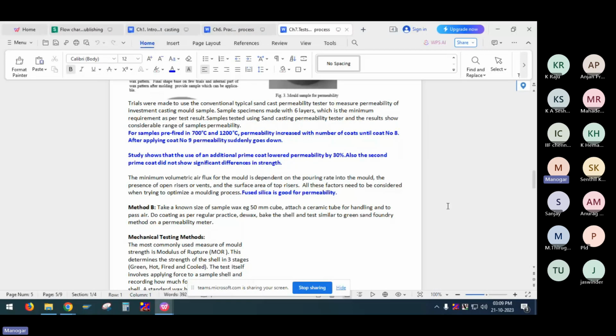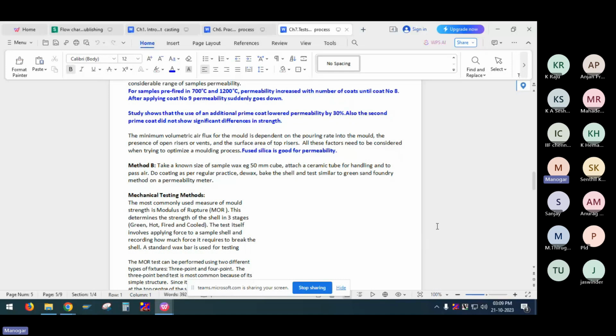And some foundries use intermittent prime coat or secondary coat. That prime coat reduces the permeability by 30%, so it is not advisable to go for the intermittent prime coat. And there is no improvement in strength also, that's what the study says. And to have a better permeability, use of fused silica is good compared to zircon flour.